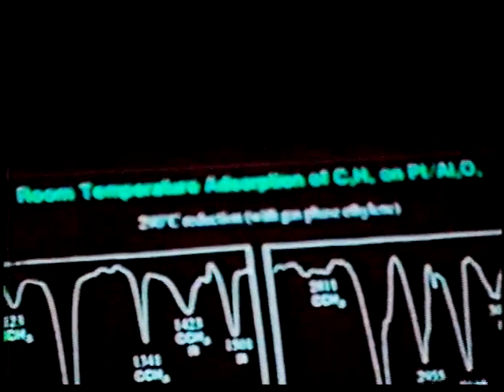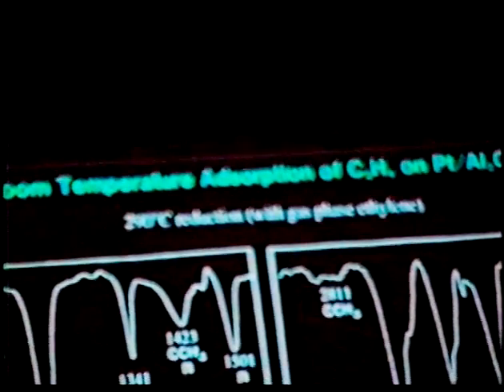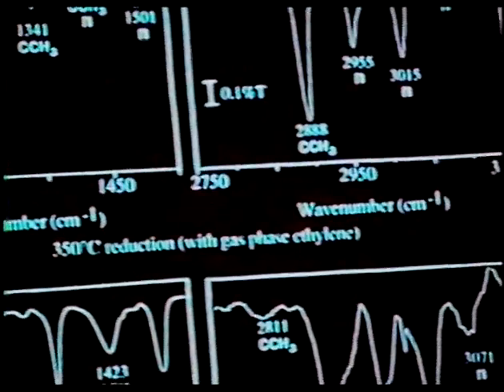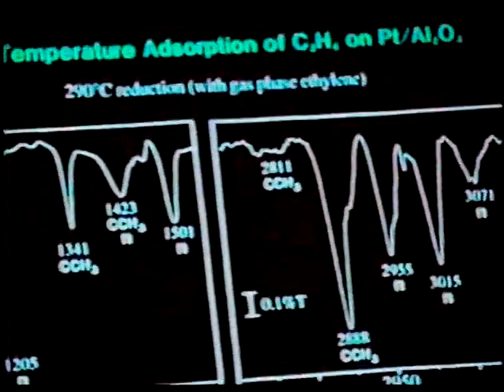Superimposed here are two different sets of spectra taken following those two different pre-treatments. In one case, can we have that focused a little better so we can see this? This is 290 centigrade. That would be the lower temperature. Down here is 350 degrees. And this is done with about 130 millitorr of ethylene present in the cell.